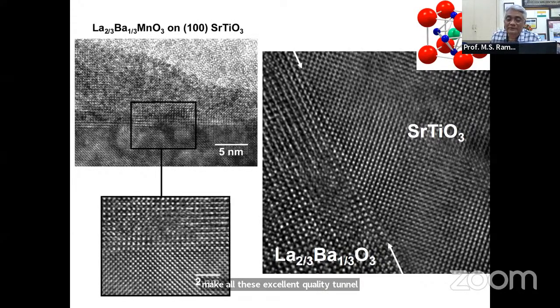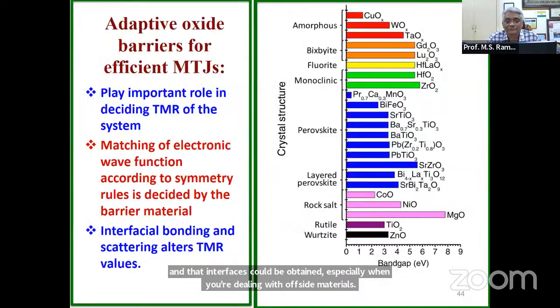And you see the interface here between strontium titanate substrate and LBO. Same would be the case with LBMO also. You see a very clean interface, and such interfaces could be obtained, especially when you're dealing with oxide materials, only with a technique like pulse laser deposition.